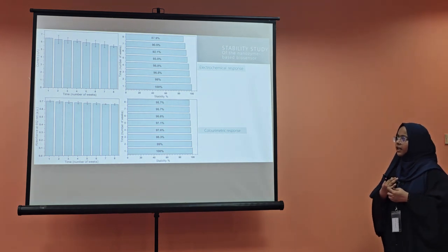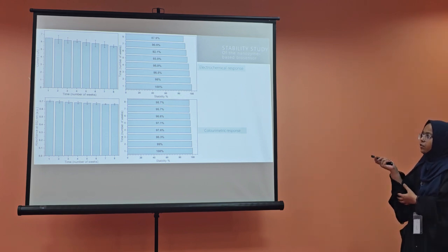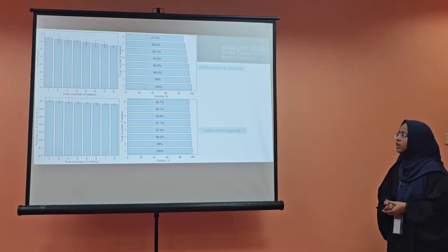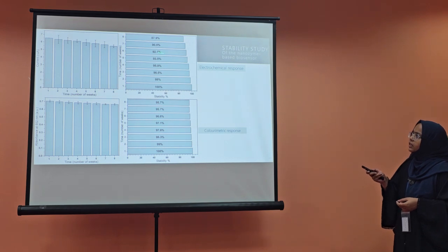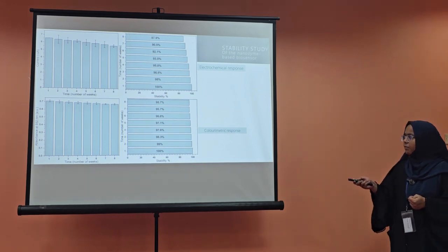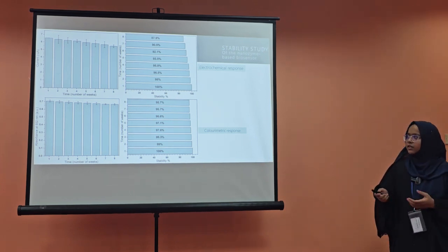Also, the stability of the trimetallic nanocomposite was assessed. The trimetallic nanocomposite was stored at 4 degrees for up to 8 weeks, and every week the immunoassay was carried out to check the electrochemical and colorimetric response. Even in the 8th week, the nanoparticle retained approximately 88% of its enzyme mimicking properties. Similarly, for the colorimetric response, it still retained about 95.7% of its enzyme mimicking activity, suggesting that this proposed trimetallic nanocomposite is highly stable.